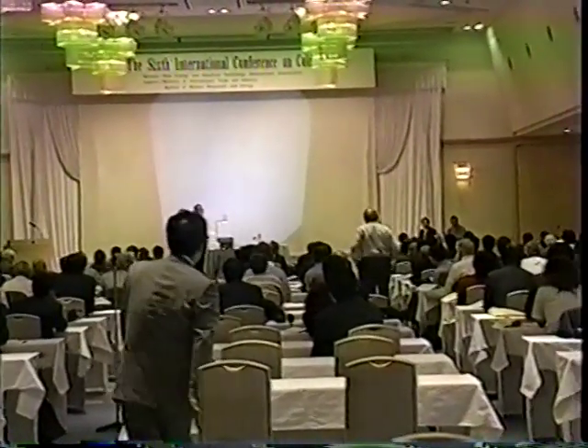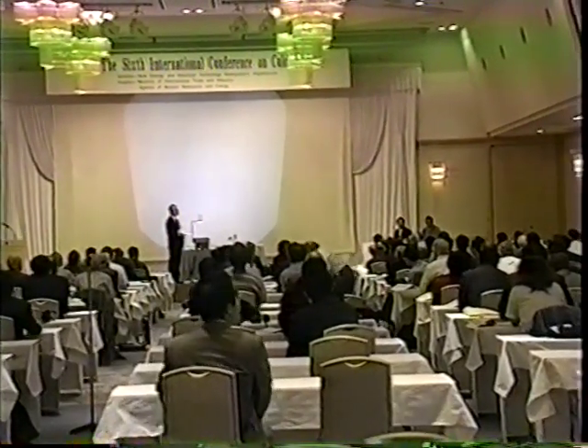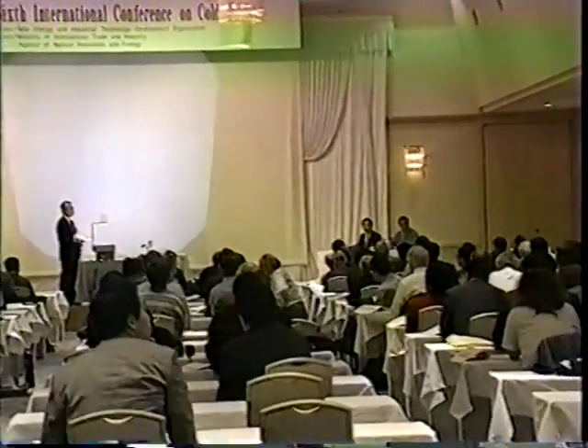So, just thinking again about the calibration, from my experience, when we use a nickel plate for calibration, several times we get some strange effects in respect to calibration using a calorimeter. So from 1992, we decided that the nickel sometimes gives a very strange effect and we decided not to use it anymore. So we use a gold plate, which is developed, or when we have the possibility, a platinum plate.